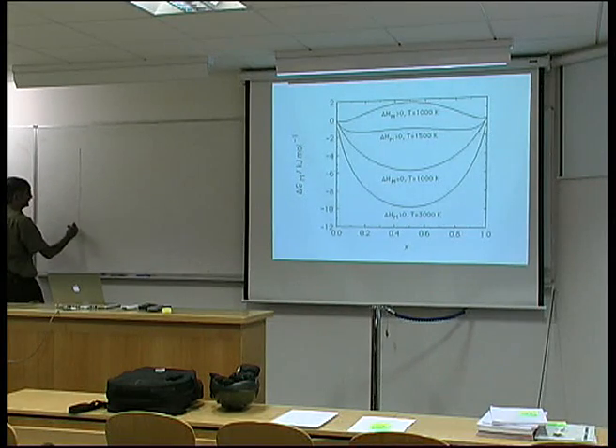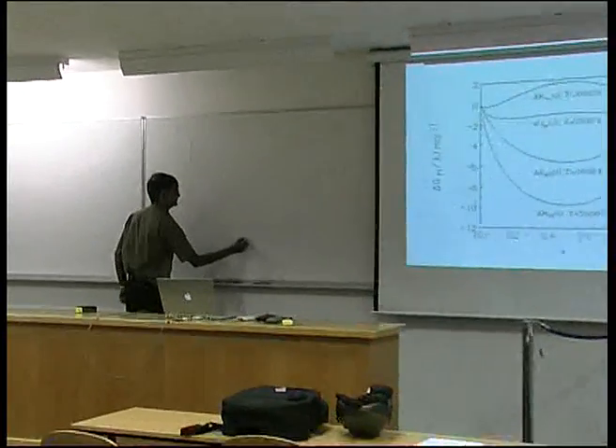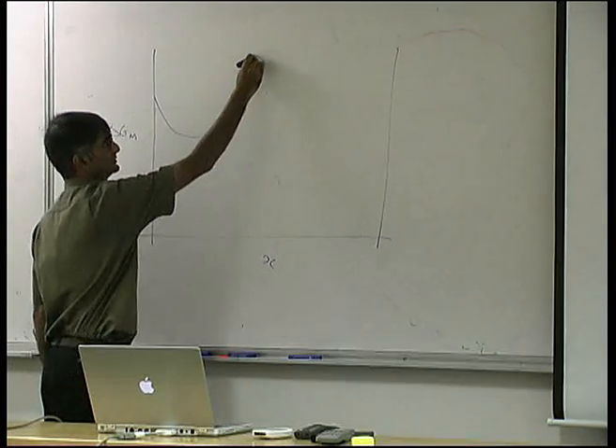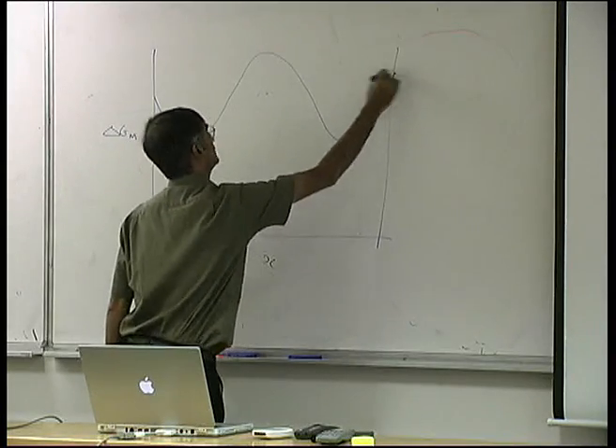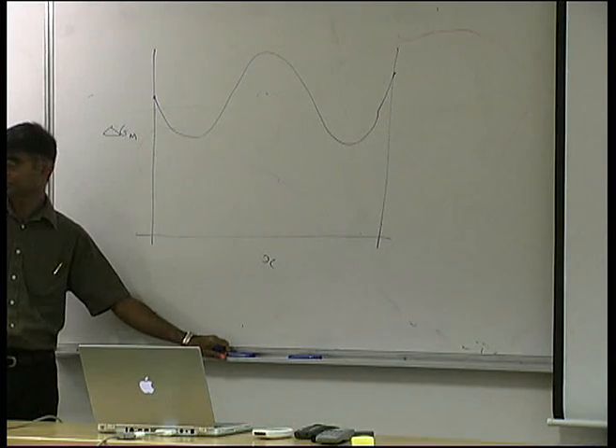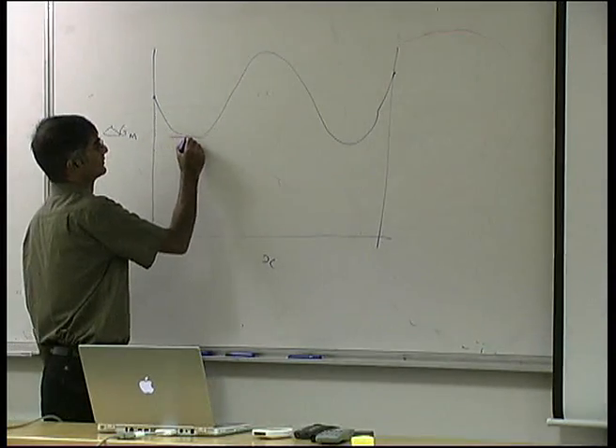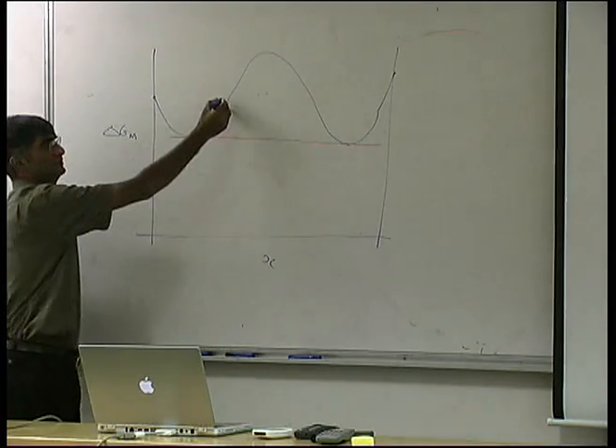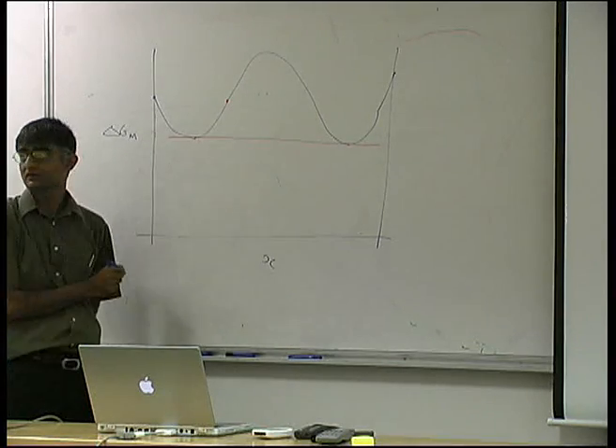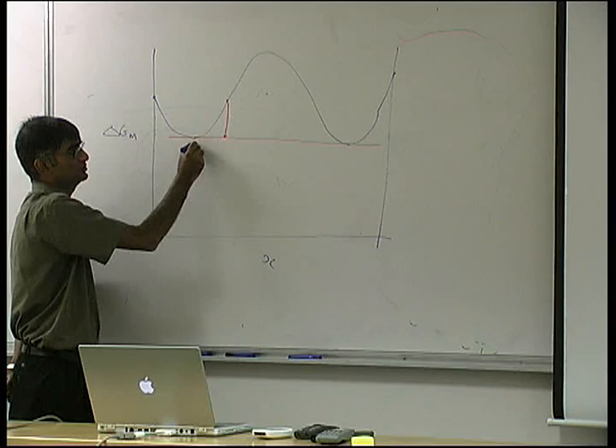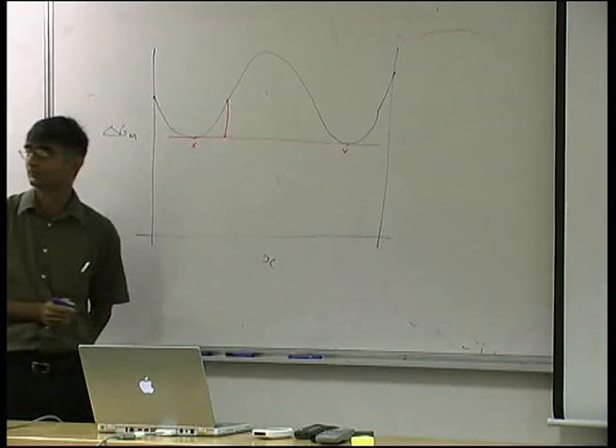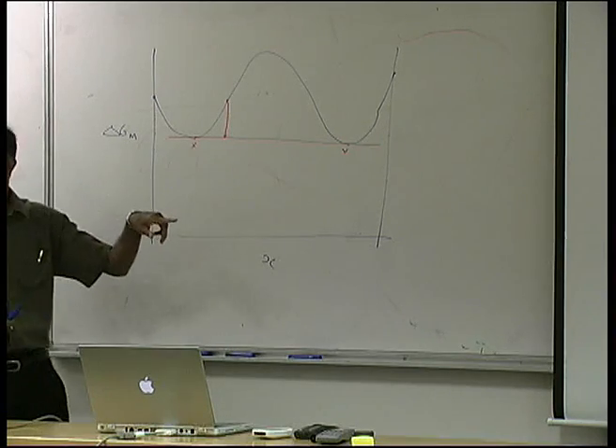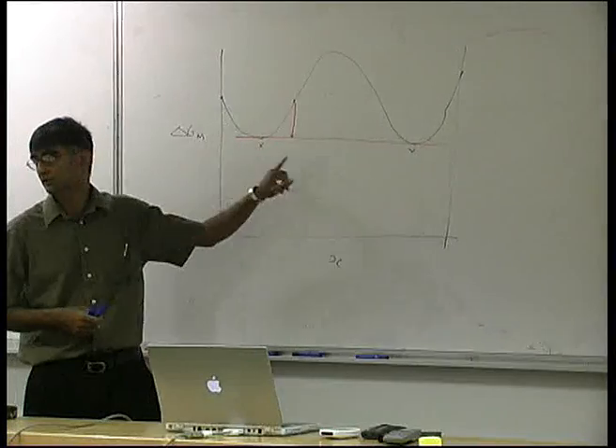If I draw that diagram again, plotting concentration X and the free energy of mixing, and I have a curve with two minima, I can actually draw a common tangent to this curve. This means that if I have a solution of any composition along here, there will be a reduction in free energy if it changes into a mixture of an A-rich and a B-rich solution.